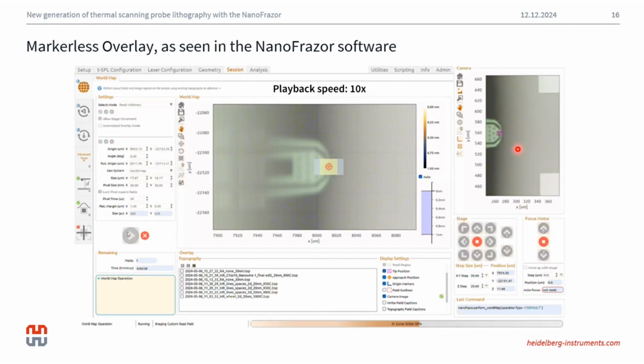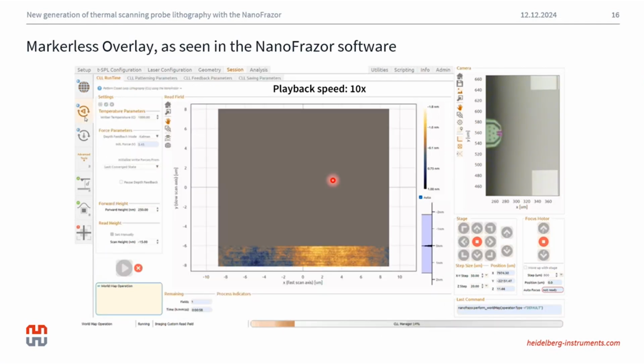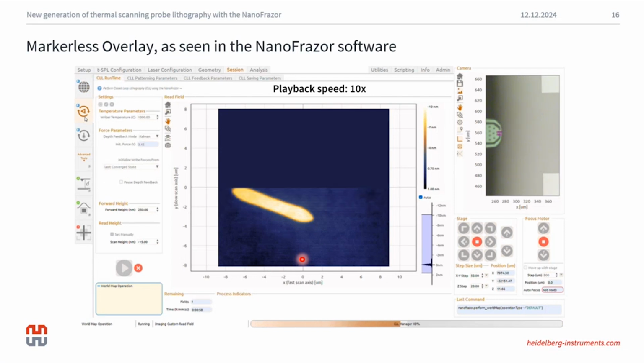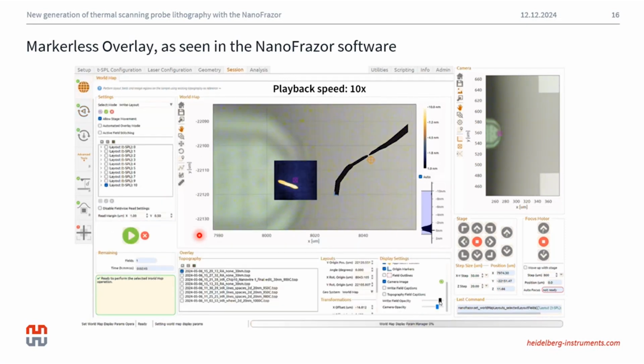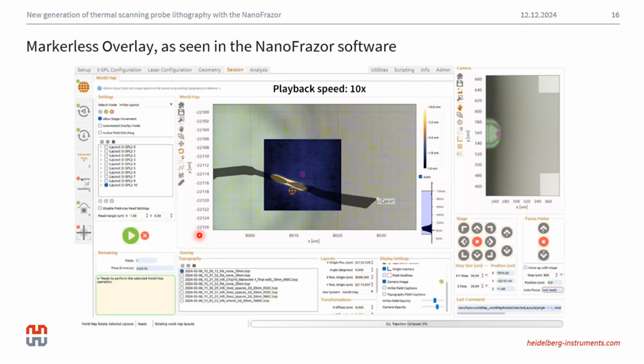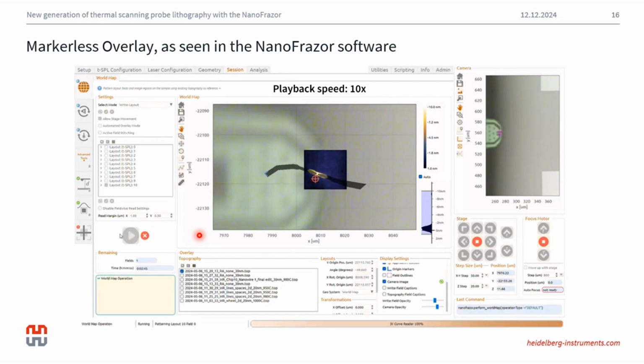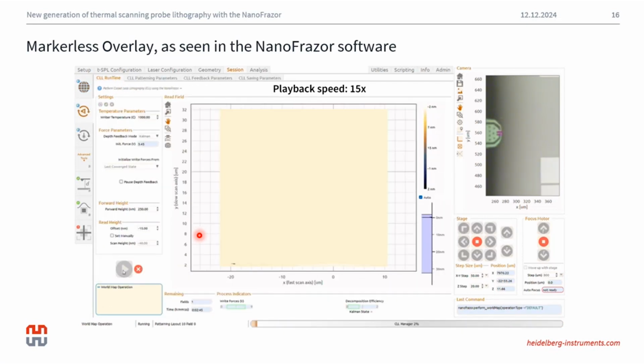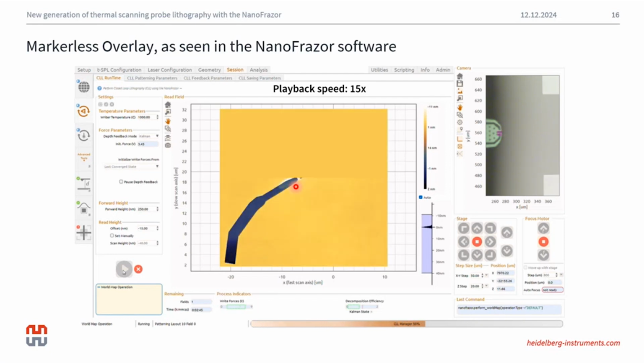So as you can see, we can move the tip very accurately to the location of the nanowire, scan the nanowire with the tip in the cold mode, then drag and drop our design of choice, rotate it, move it in the way that we want, then launch the pattern. And this is a live view of the contacts that are written and the topography of these contacts overlaid on top of the nanowire.